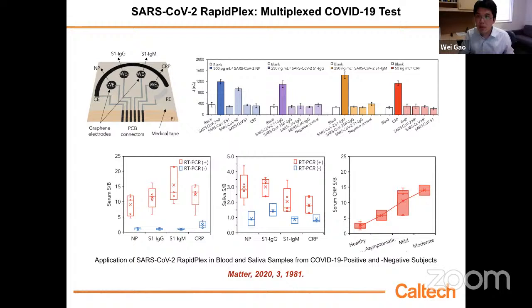And we're actually looking at the inflammatory biomarker level versus the severity of the symptom. Basically, we found that with the increase of symptom, we observe this increased CRP level, indicating that we can actually assess the severity here.